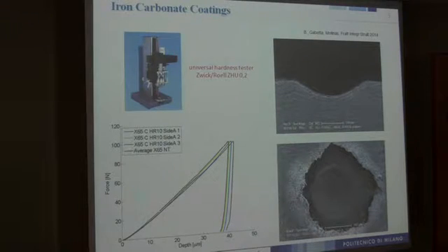The adhesion characteristic of this coating to the steel substrate can be evidenced, for instance, by an indentation test. This is one of the examples of the result that one can obtain by indenting with a Rockwell tip these kinds of material systems. As you can see here, the scales are removed, especially in the piling up area of the indenter imprint.